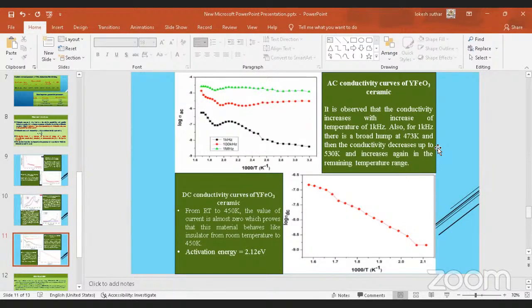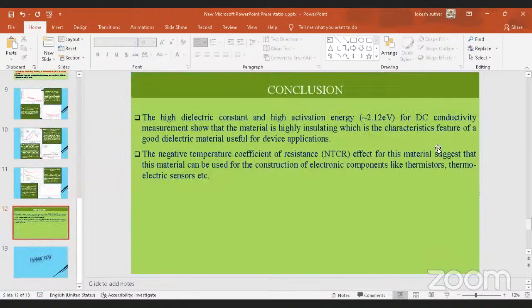We have calculated the activation energy, which was observed around 2.1 electron volt from the slope of the DC conductivity curve, which shows that the material is showing the NTCR effect. And this is the conclusion. The high dielectric constant and high activation energy, around 2.12 electron volt for DC conductivity measurement, show that the material is highly insulating, which is the characteristic feature of a good dielectric material and is useful for device applications.